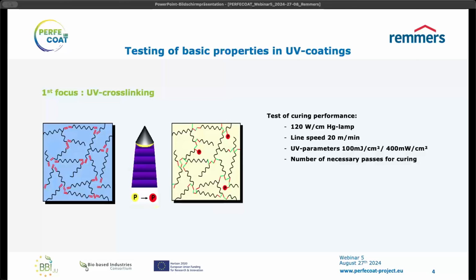The first thing we focused on is of course the UV cross-linking itself, because that's the main property we need. Just some explanation of how we did the testing. We were doing the curing with a 120 watt per centimeter mercury gas discharge lamp. We have set a line speed of 20 meters per minute for the curing, and we adjusted the UV parameters for 100 millijoule at 400 milliwatt per square centimeter. And then we simply checked how many passes under the lamp are necessary to reach a sufficient curing.